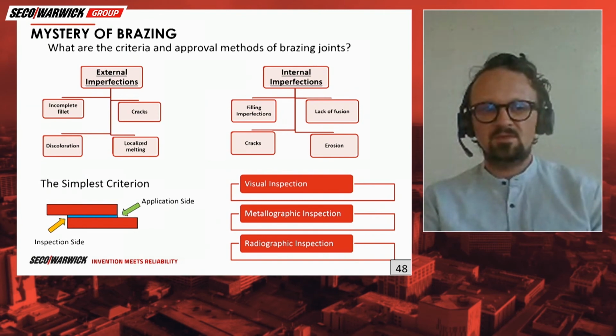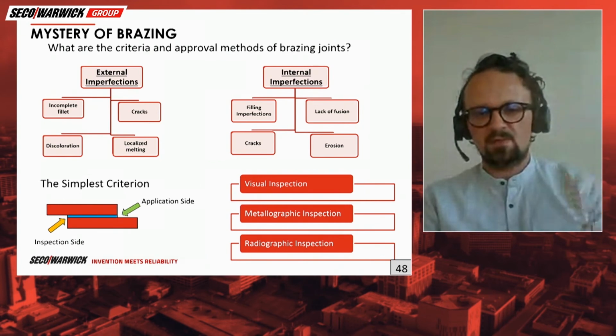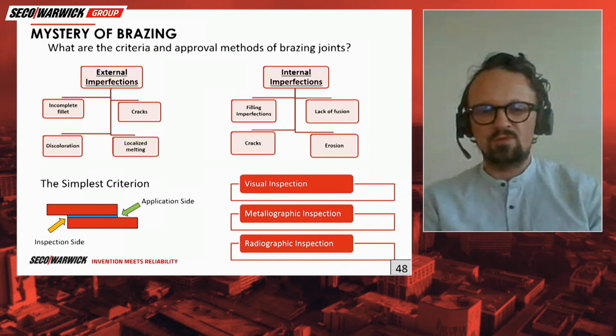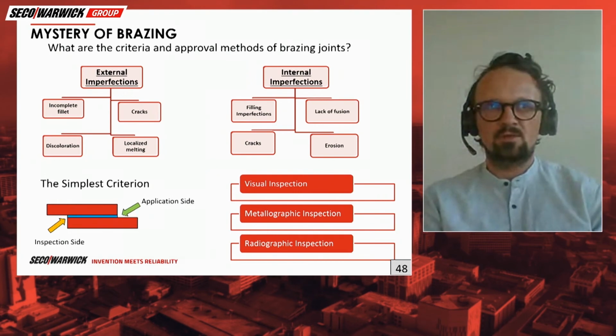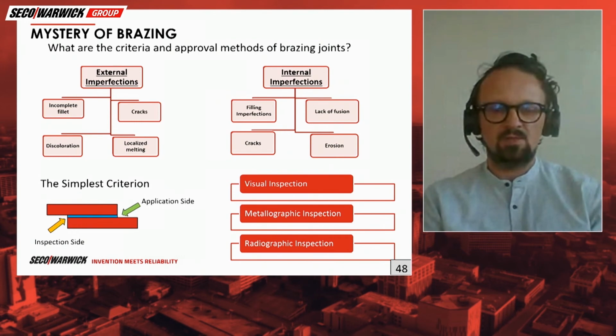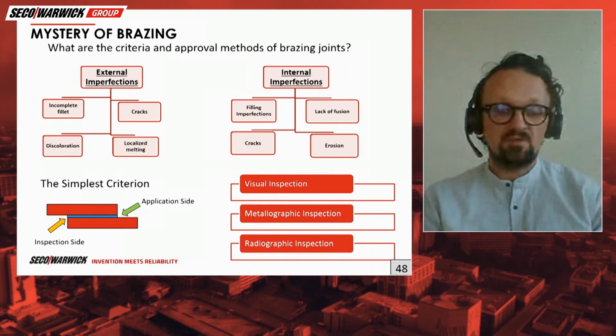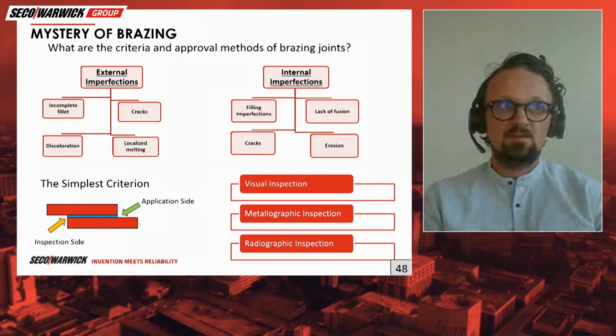One of the simplest criteria is that you check the joint from both sides. If you apply the braze material from one side, it should flow through the joint to the other side, and if you see the flow on the other side, it means at least in 50% of the cases that it went okay. It works. Maybe not good. When you cut it up, you might see a lot of defects inside, but you are on a good track. And for some applications, that's enough. For other, more critical applications, we should perform metallographic inspection and leak tightness testing, and radiographic should be used rather as failure analysis.